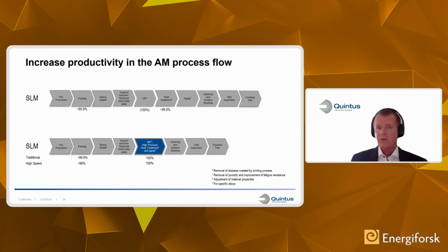If you look at the typical AM process flow and compare it with what can be achieved with Quintus high pressure heat treatment, typically you would print to perhaps 99.9%, and then you would have the HIP, and then you would have your subsequent heat treatments done in separate thermal processing units. With the Quintus high pressure heat treatment, you can actually keep the product in the HIP and do your heat treatment and aging in the same HIP cycle.